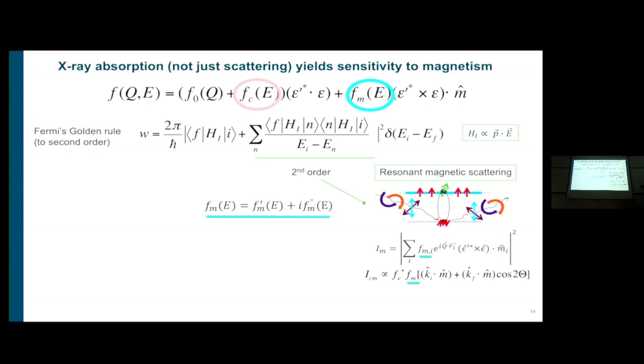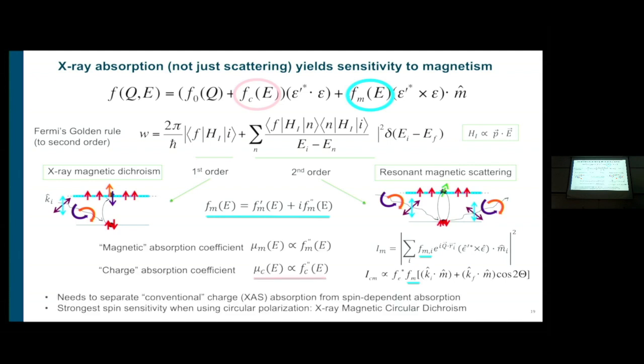But how about absorption? Absorption, we said, is related to the imaginary part of these complex scattering factors or scattering amplitudes. And absorption is a first order process. You come in, you excite an electron, and you become sensitive to the spin polarization of the valence band or the valence orbital. And this technique is much more simple. So we call it magnetic absorption.